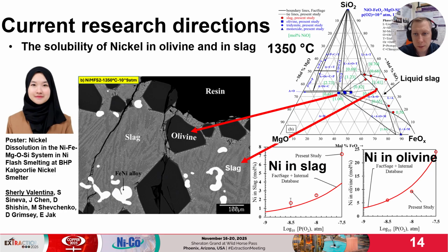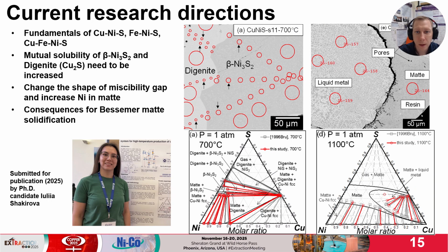So to summarize some of the current research directions, they are the solubility of nickel in olivine in slag, for which we have a poster at this conference. These were supported by Kalgoorlie nickel smelter until it's shut down. Another research direction is an improvement of copper-nickel-sulfur system and related systems. The miscibility gap between Cu2S based matte and metal is not described very well by the current model and proved to be very challenging to fix.